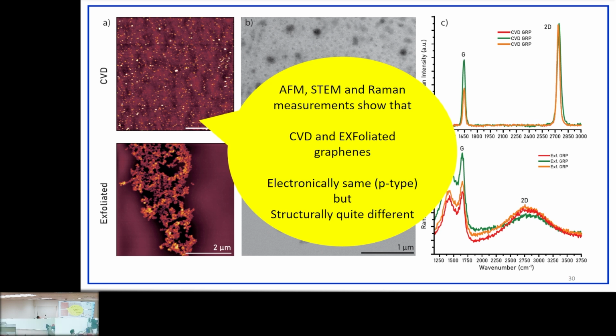Some characterizations, as you see, we have AFM images. The AFM images of CVD and exfoliated graphene are quite different. Here we have a lot of patches, flakes, but in CVD we have a nice surface. So again, STEM measurements and Raman signals. You see, we have very nice, almost single crystal graphene, but here, because of fragments and flakes, we don't have those sharp peaks. And so this slide says that those materials are not the same. They are different.